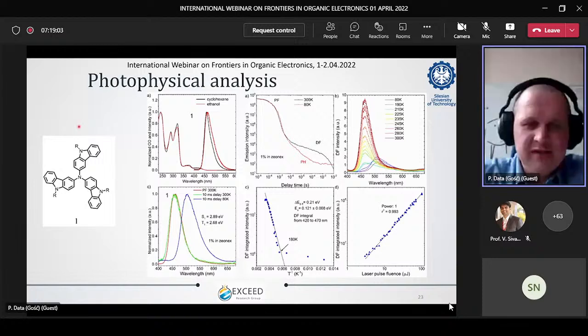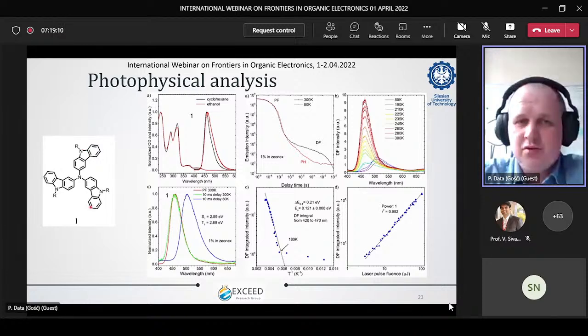This is one of the examples of our molecule which had TADF, but they were not ambipolar. They were pure donor. They had donor character. The emission doesn't matter if that was the polar or non-polar solvent. They were quite similar, but we observed delayed fluorescence emission.